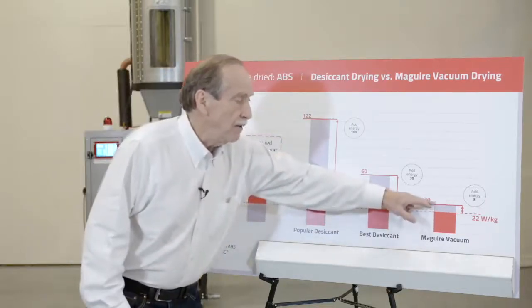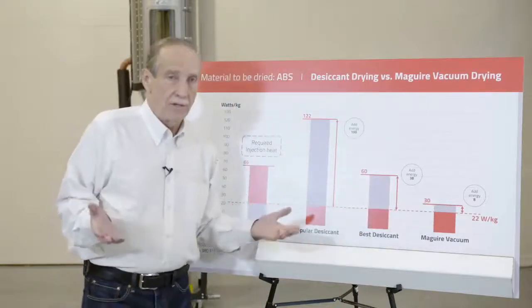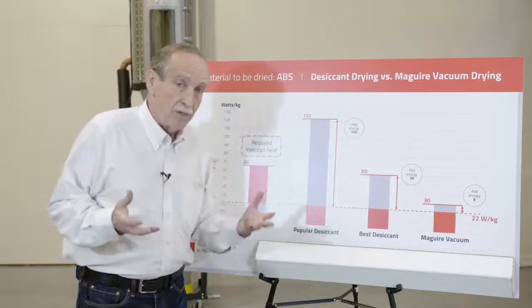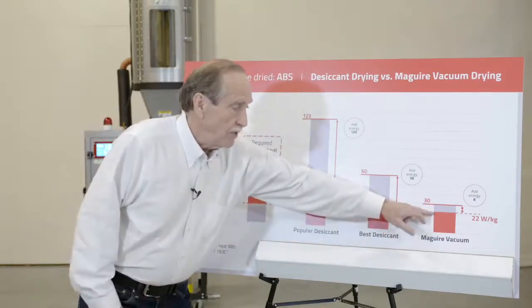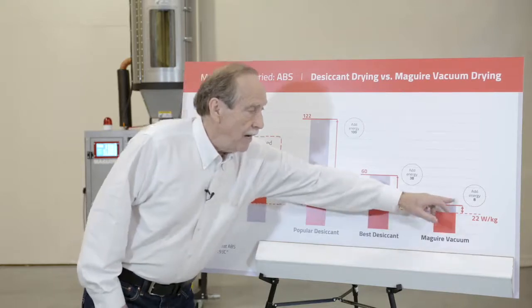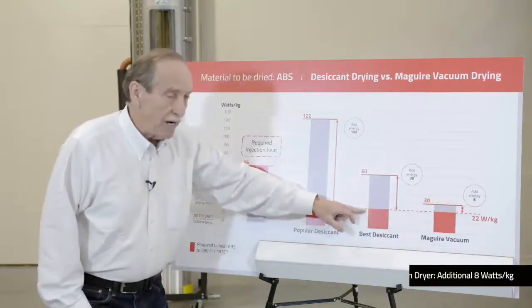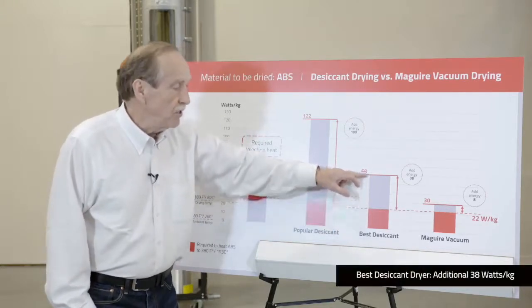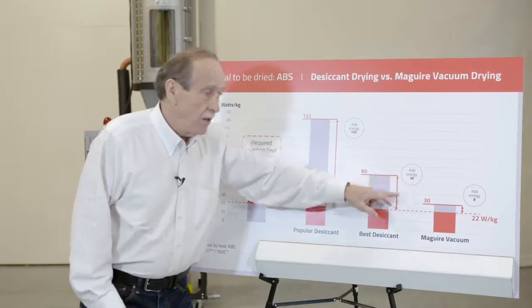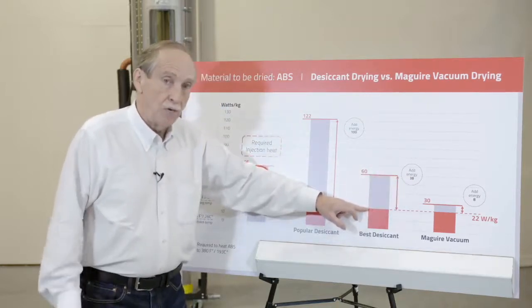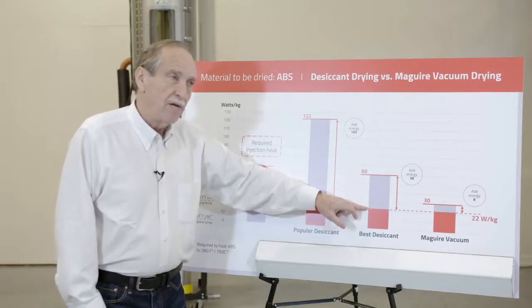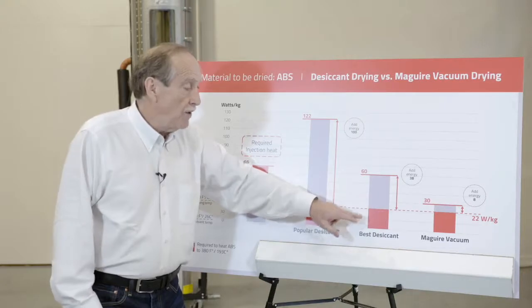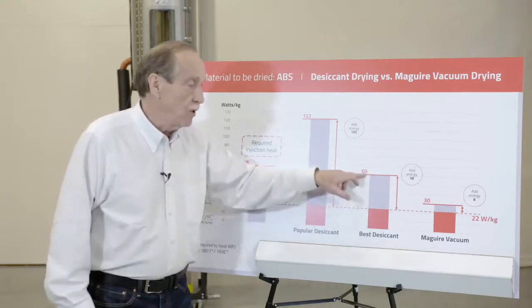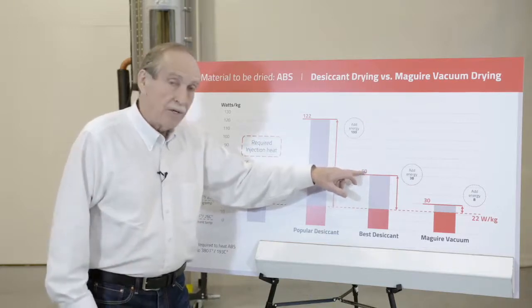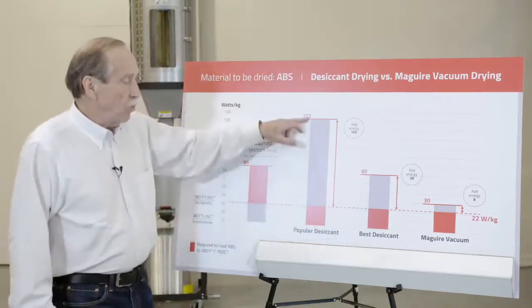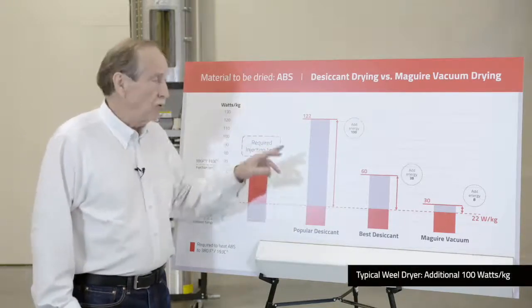It's what you use above that line that is what I'll call wasted, or its sole purpose is to dry the material. This is what vacuum drying does. It uses an additional eight watts per kilogram. This is what the best desiccant dryer on the market we could find does. It uses an additional 38 watts per kilogram. The best on the market, by the way, was a European dryer, and it was a small dryer, and it had every energy saving option you could imagine built into it. And this is the number they claimed. Our tests proved that number to be correct, that 60 watts per kilogram was correct, and that was what they claimed. But this is what a typical wheel dryer actually uses, 122.